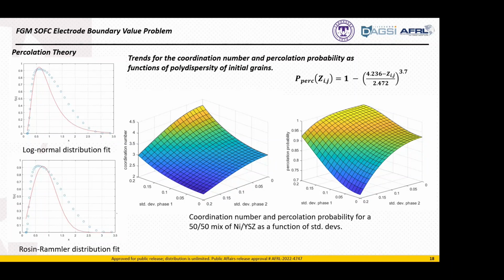Yeah, I understood, because you're looking at the percolation of density, so that there is a minimum of nickel or nickel oxide you need to start with, but there is also a maximum. So I'm wondering if your optimization can. There's only a very narrow range, actually. Practically, you can use the concentration between the two.